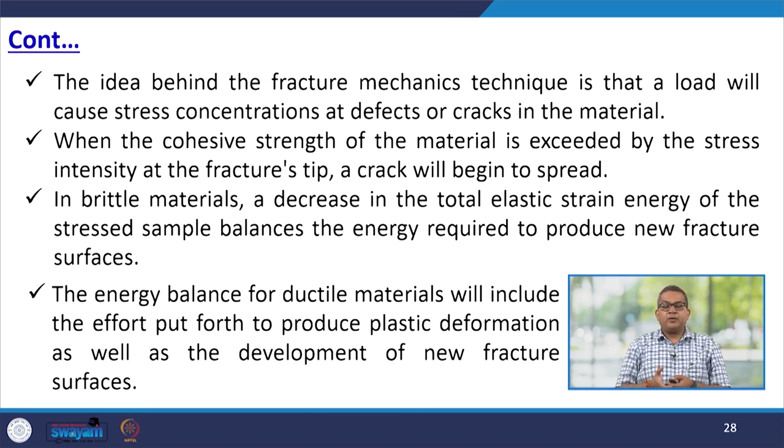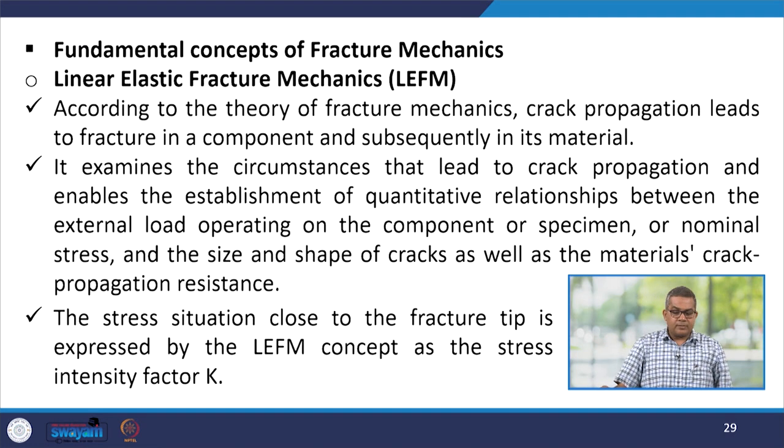The idea behind the fracture mechanics technique is that the load will cause stress concentration at defects or cracks in the material. So, when the cohesive strength of the material is exceeded by the stress intensity at the fracture tip, a crack will begin to spread. In brittle material, a decrease in the total elastic strain energy of the stressed sample balances the energy required to produce new fracture surfaces. The energy balance for ductile material will include the energy put in to produce the plastic deformation as well as the development of a new fracture surface.